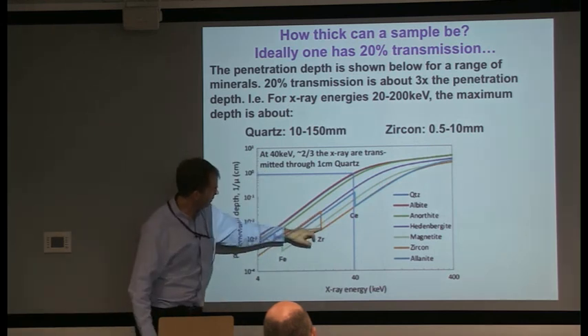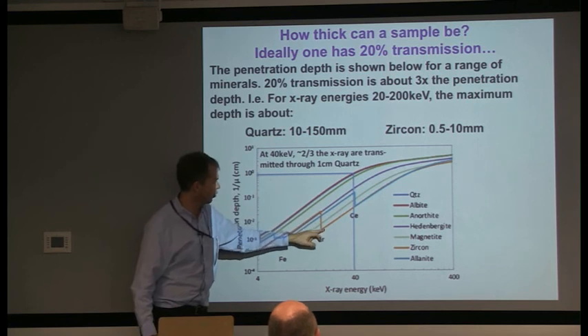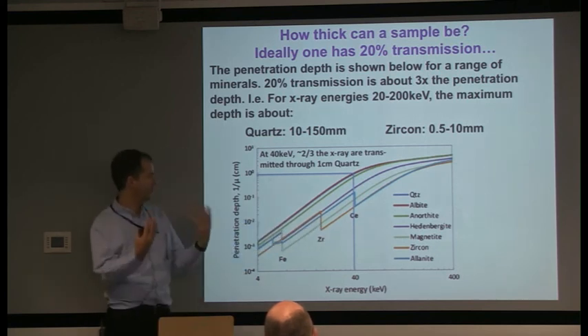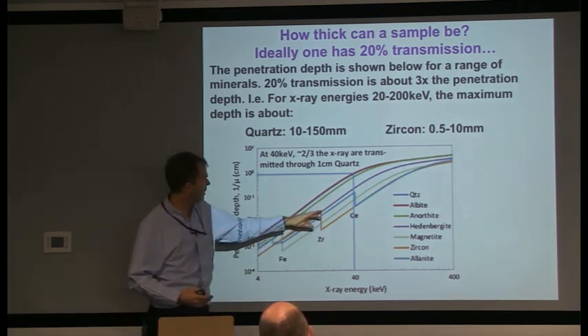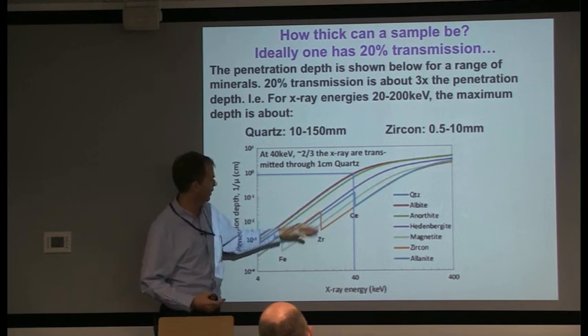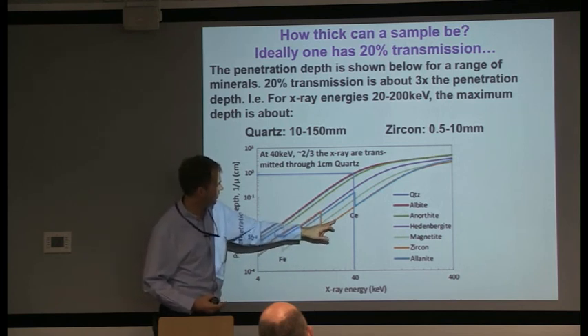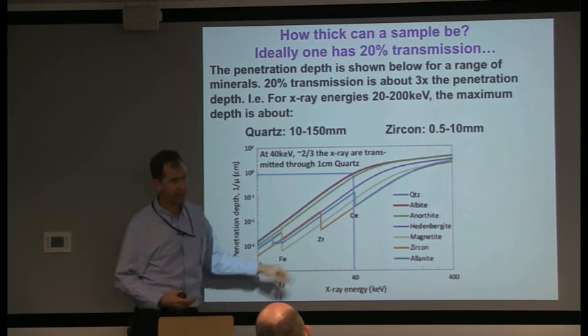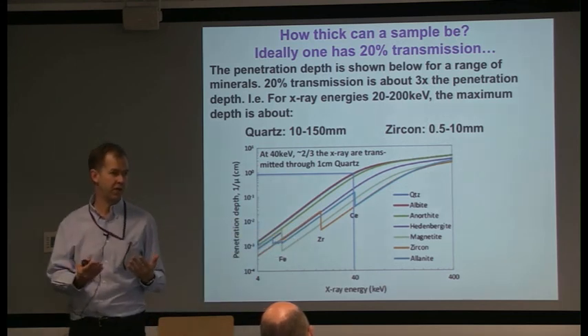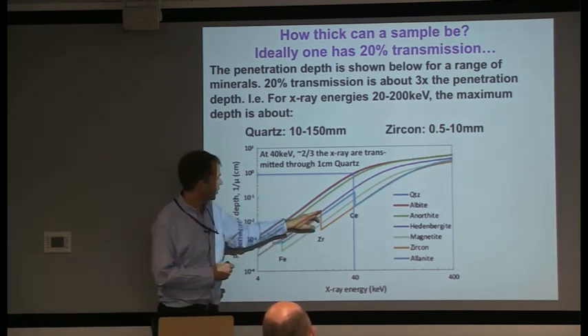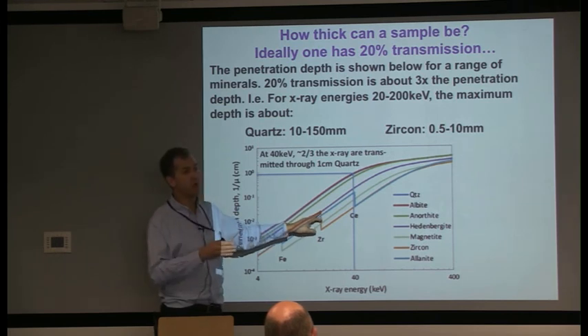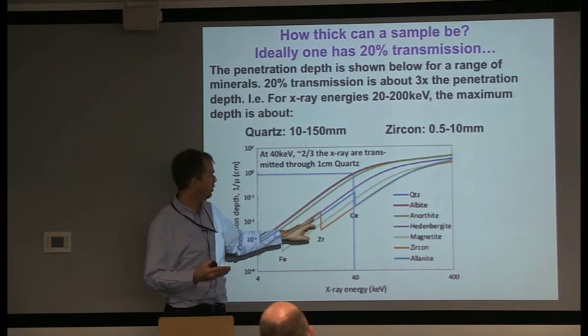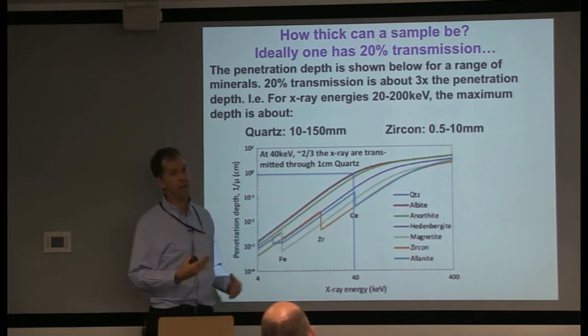You also have these edges, which are the electron orbital interaction - rather than the cloud of electrons, it's coming up to an energy at a K edge or an L edge. The nice thing is we can scan above and below that and get very different attenuation, so you can tell motion of your elements - not speciation, but with much higher resolution - if we scan above and below an edge.